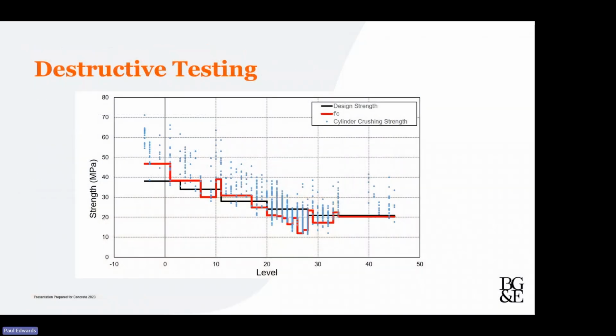And you can see that, if you cast your mind back to that Schmidt hammer test, this is again for core walls, you can see that the further detail provided by the destructive testing bore out the higher level information found under the Schmidt hammer testing. And the black line is the design strength of the core wall. So anything below the black line, following the ACI 214 method, would be an area of concern and need for intervention.